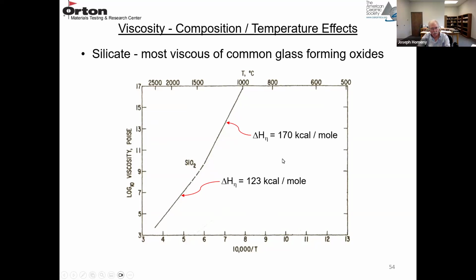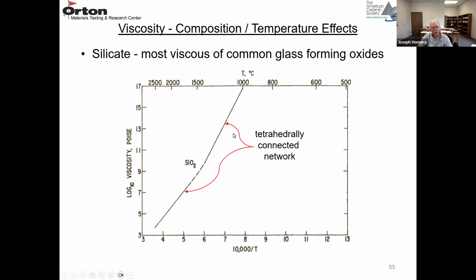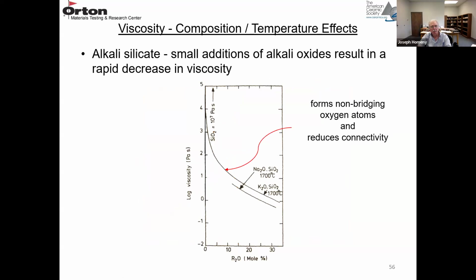So that's for a silicate glass. And in this whole temperature region, you have these SiO4 tetrahedrons. They're all tetrahedrally connected in the network. So they're all bridging oxygens, no non-bridging oxygens. So when you add an alkali, you have an alkali silicate glass. Small additions of alkali oxides really decrease the viscosity.